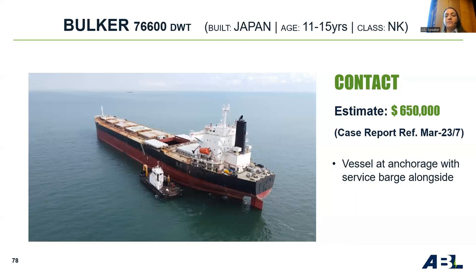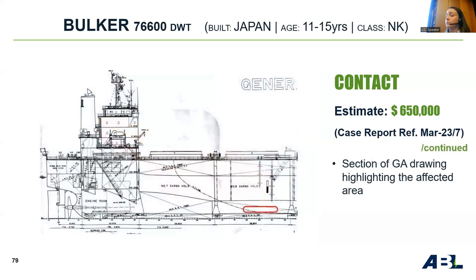The crew went down to inspect the tank and found indentations on the hull plating and stiffeners between frames 78 and 93, plus water spraying in through a horizontal crack in the shell plating in way of this damage. Here's the location of the damage, which is marked up on the ship's general arrangement.